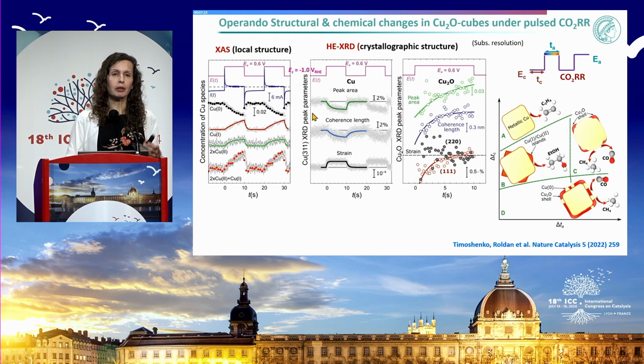So when you look at these materials at the synchrotron, you can follow with these applied potential pulses how we get the oxidation of this material. We can get copper 1 species, copper 2 species, and X-ray absorption spectroscopy gives you ordered and disordered phases. This is important because sometimes the catalysis is not being done, most of the time it's not being done by the perfect crystalline phases. If you combine with XRD, you can learn also what the crystalline component of your material is doing.